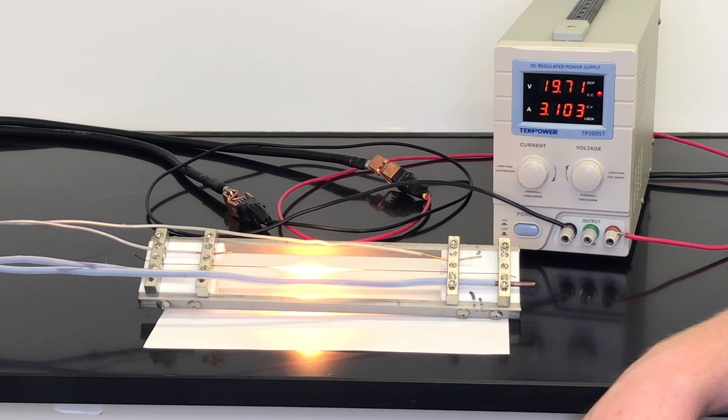Once that hot spot reaches 500 or 600 degrees in air, the carbon nanotubes at that spot will burn, and the yarn will break.